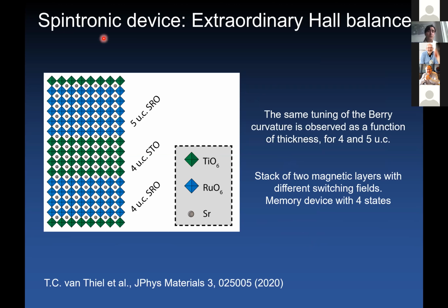And one thing that you can do is you can make some spintronic devices. So one useful spintronic device is called the extraordinary Hall balance. So that's a device that functions as a memory device with 4 states. So it's a device in which you stack 2 magnetic layers with different switching fields, and possibly also with different sign of the anomalous Hall effect that allows you to distinguish between different states as a function of magnetic field. So in order to realize this type of spintronic device, we fabricated heterostructures that incorporate 4-unit cell of strontium ruthenate, 4-unit cell of strontium titanate, and 5-unit cell of strontium ruthenate. So here you have strontium ruthenate layers that are decoupled by an insulating barrier. So there is no charge transfer across this barrier.